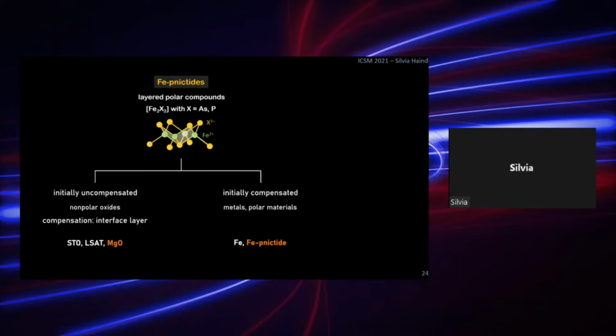So let me summarize the classification of iron pnictide hetero interfaces. We can divide them into initially uncompensated ones, which lead to a compensation mechanism that is responsible for the interface layer formation. We find this when we grow the iron pnictides on nonpolar oxide materials like STO, LSAT, and I will show later some example on NGO. We can have clean interfaces, which we call initially compensated interfaces, and this is when we grow these iron pnictides on metals or polar materials. And you have seen the examples of iron, and I will demonstrate then the example of iron pnictide hetero interfaces.